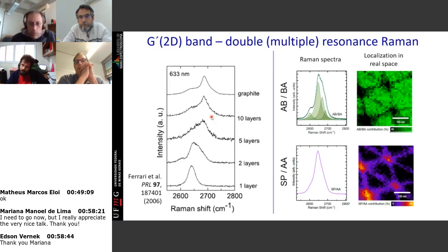When we think about phonons, electrons, you think about something that is in the entire material, right? You define a periodicity of the unit cell, and then you replicate this thing, and what happens inside one unit cell will happen all over the material, with a given periodicity, etc. But what we see here, and again, this is 100 nanometers, so this entire range here is like 300 by 300 nanometer, is that the phonons that you see here are different in frequency from the phonons that you see here. So that specific frequency is localized at this region.